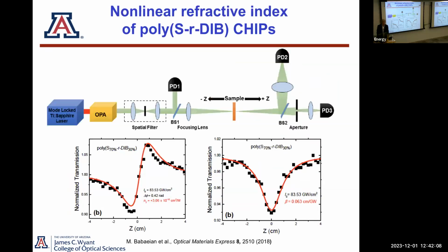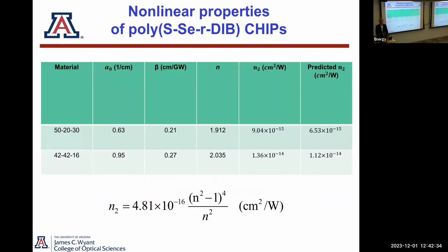We also looked at the nonlinear properties. I promised a little bit about nonlinear stuff. We did look at the nonlinear properties of these materials early on as well, using something called the Z-scan method. In particular, they have pretty high nonlinearities. The sulfur-based systems are about the same as silicon nitride, which is a moderately nonlinear material. And the selenium-based systems have a nonlinear index almost as high as silicon, which is quite high, but also have low nonlinear absorption, which is an important consideration. And it all agrees well with a basic framework that we adopted from the early literature of nonlinear optics.